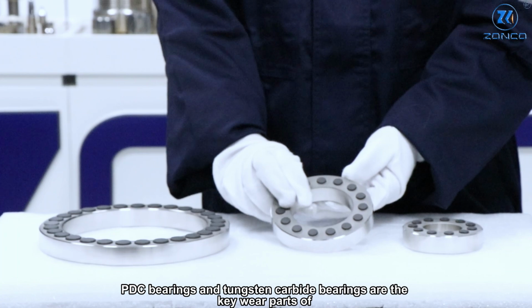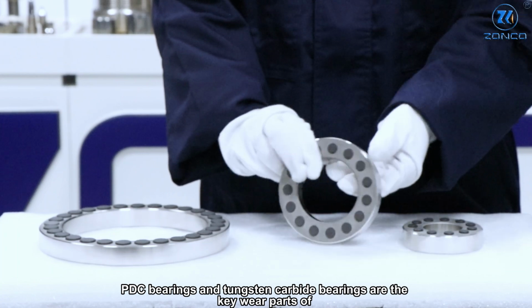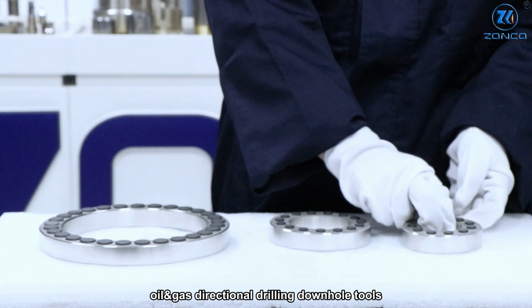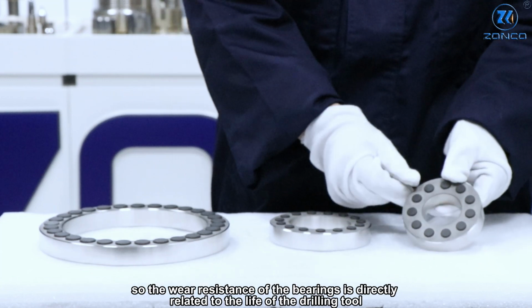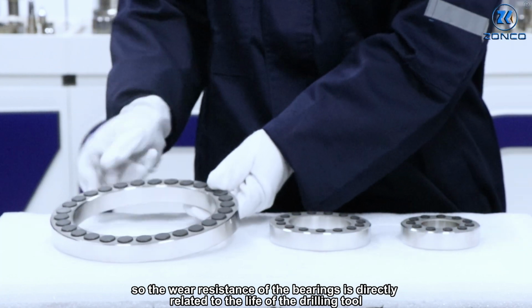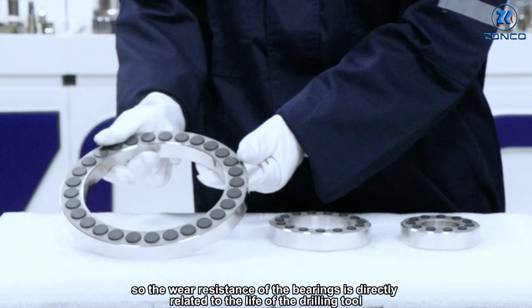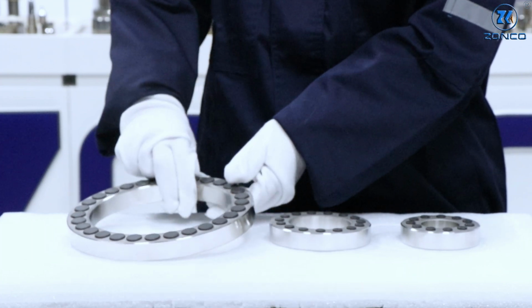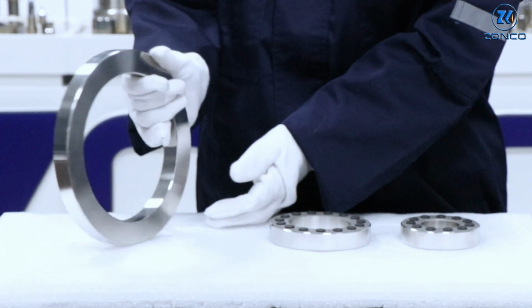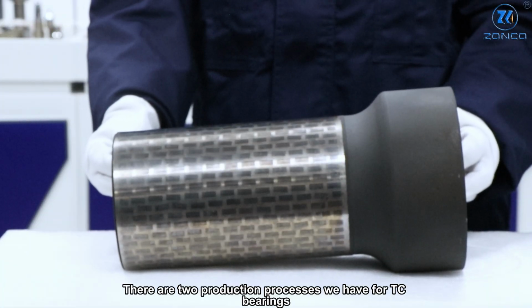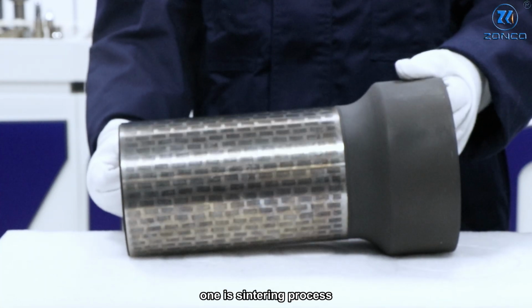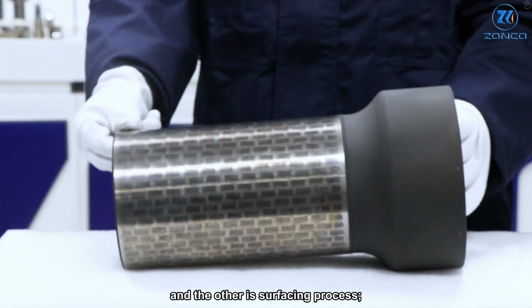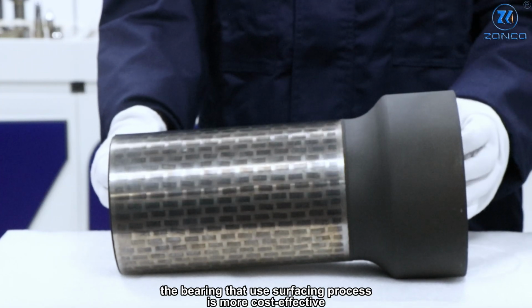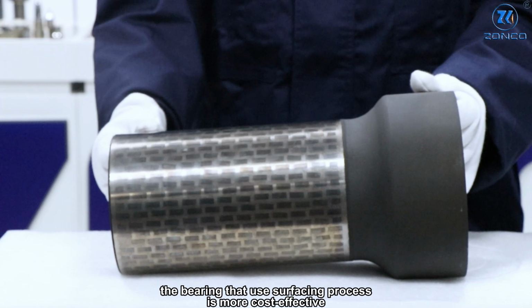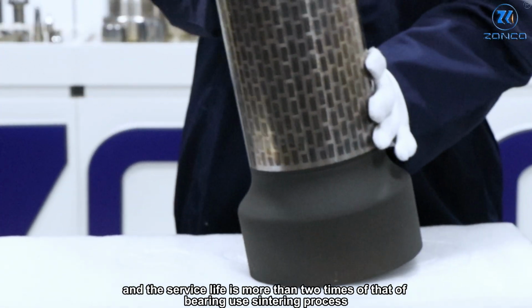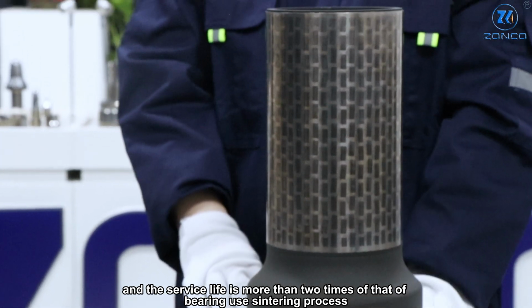PDC bearings and tungsten carbide bearings are the key wear parts of oil and gas directional drilling downhole tools. So the wear resistance of the bearings is directly related to the life of the drilling tool. There are two production processes we have for TC bearings. One is sintering process, and the other is surfacing process. The bearing that uses surfacing process is more cost-effective, and the service life is more than 2 times that of bearings using sintering process.